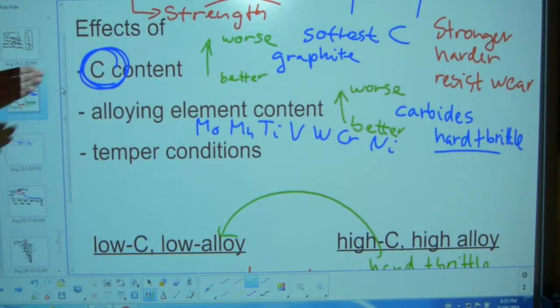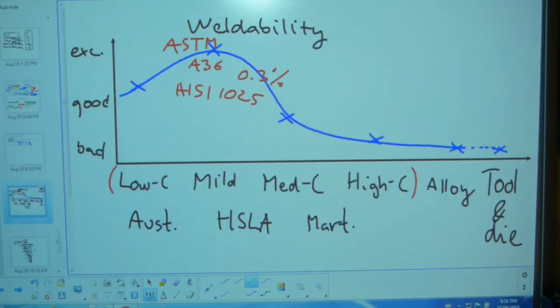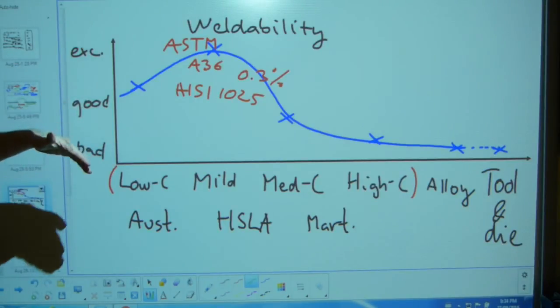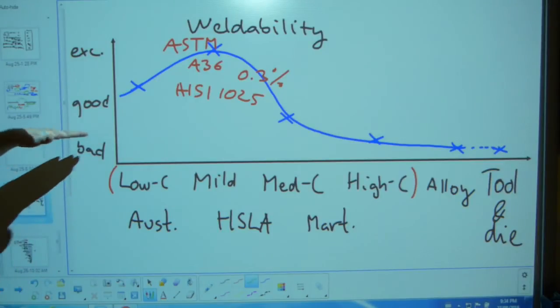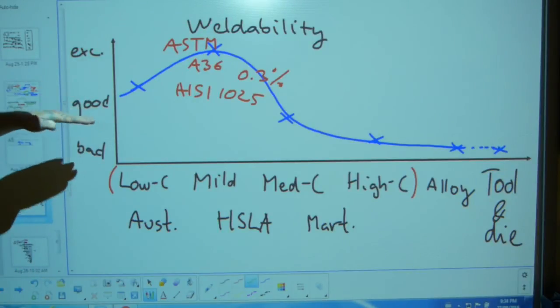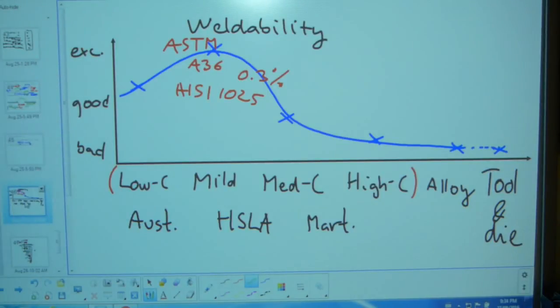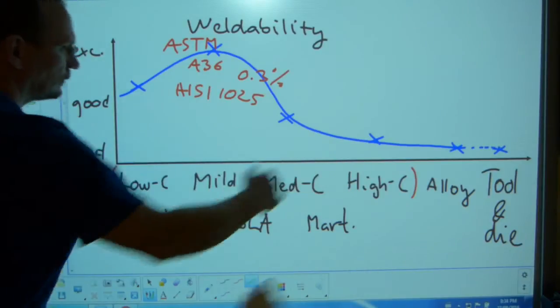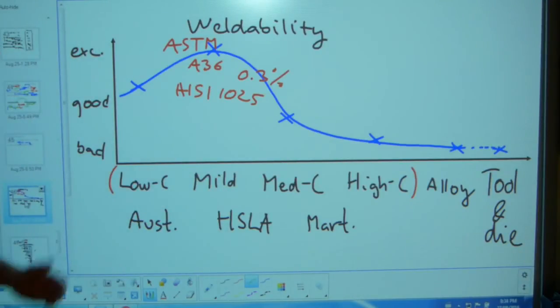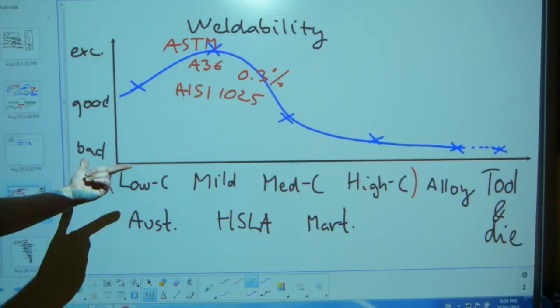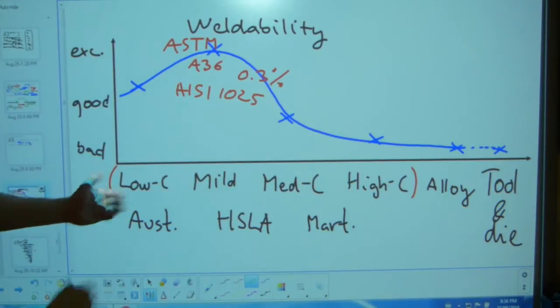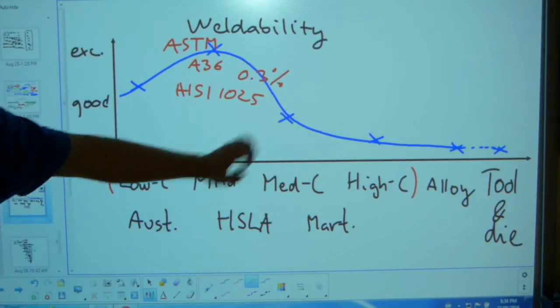This is how carbon and carbides and graphite and this temper and the existence of austenite affect weldability. To put it together, all of them together, I have them on a graph that looks like this. On the vertical axis, I just invented this. I have just subjectively assigned very poor to bad to miserable to somewhat okay, good, better than good, excellent. So these adjectives are on this side, and I have the steels listed on the horizontal axis. Some steels, you see the carbon content going up, low to mild to medium to high carbon content going up, and there are some other steels. I'm going to explain those in a sec.